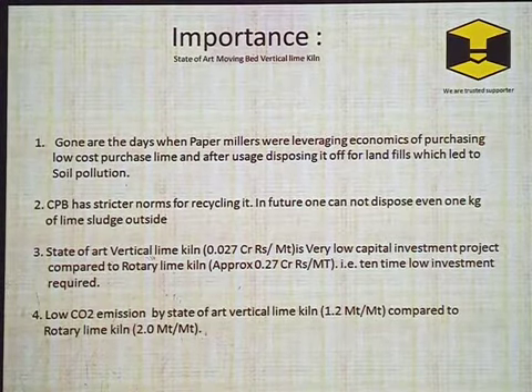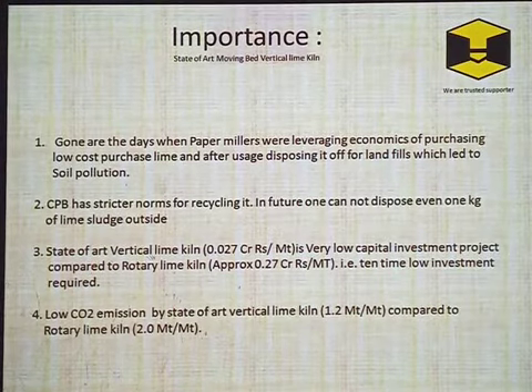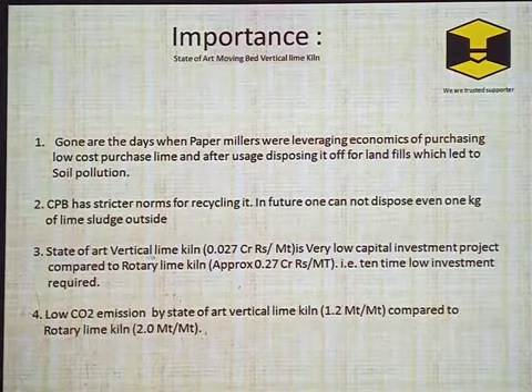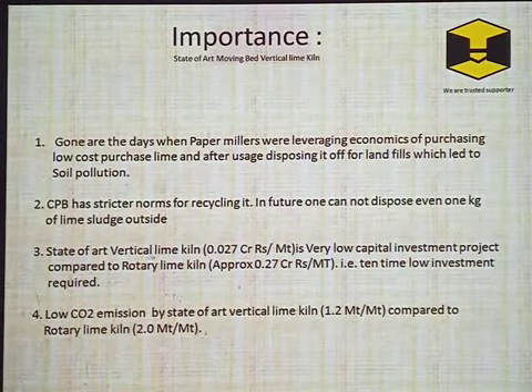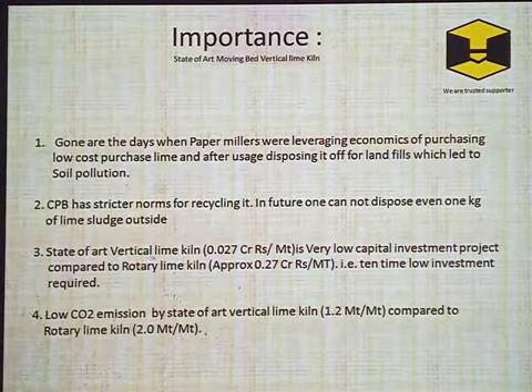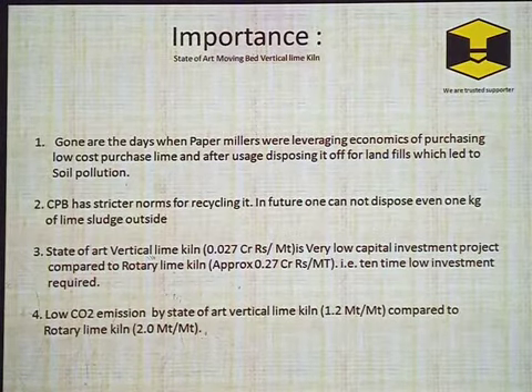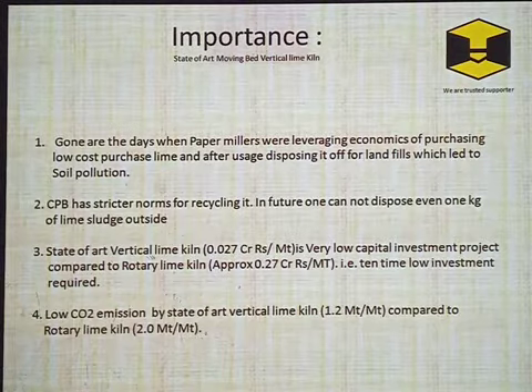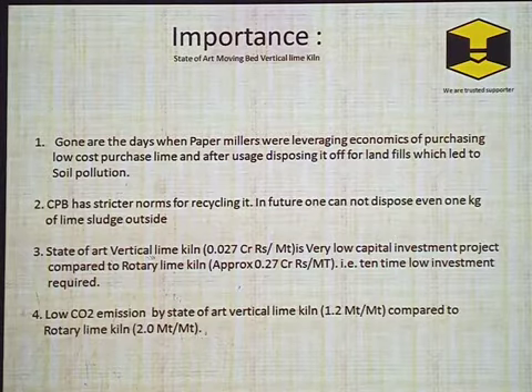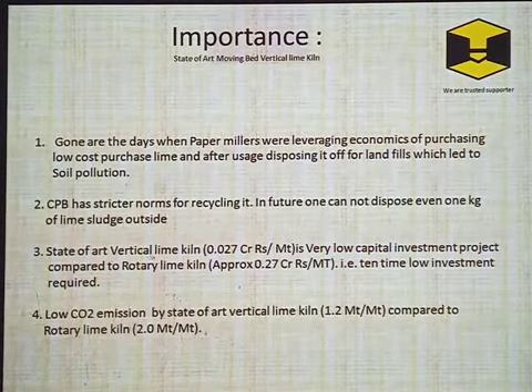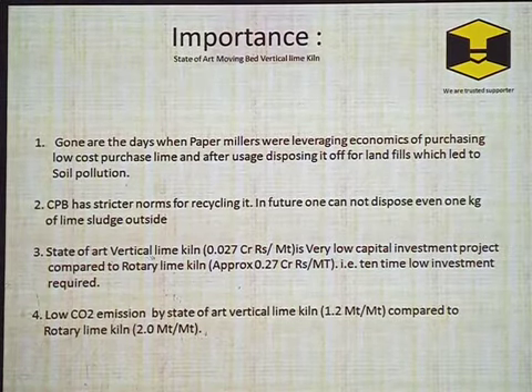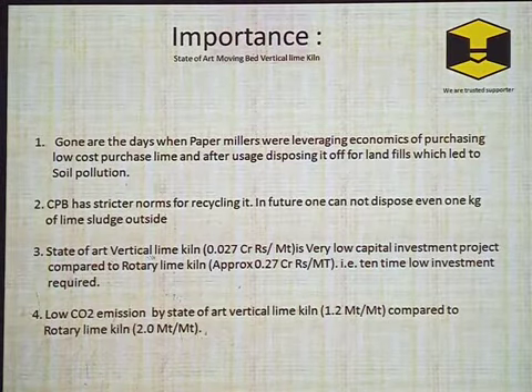The state of art vertical lime kiln requires very low capital investment, that is 0.027 crore rupees per metric ton of lime, whereas a rotary lime kiln requires high capital investment, approximately 0.27 crore per metric ton. So the capital investment for installing a state of art vertical lime kiln is 10 times lower compared to a rotary lime kiln. Emission is also very low due to reduced fuel oil consumption, it is only 1.2 metric ton per metric ton of lime produced.